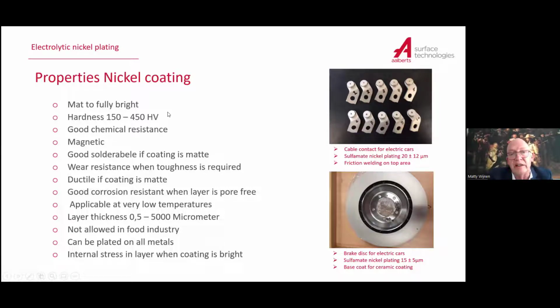Now, the hardness of electrolytic nickel is just about 150 to 450 HV hardness figures. That means dull nickel is 150, bright nickel is 450. There's good chemical resistance of nickel itself. It's magnetic. That can be an advantage and can be a disadvantage. If it's an advantage, you can use it as a magnetic switch. If it's a disadvantage, you can't use it when magnetic switches are in the neighborhood. It's solderable if you have a matte coating, only then, not when the layers are bright. Wear resistance and toughness, I already explained.